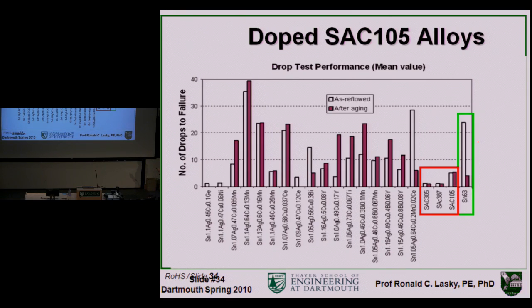So you can see SAC 305 is not too good. SAC 105 is better. But what Dr. Lee found was that if you added just tiny amounts, this is essentially SAC 105 with 0.1% manganese, just tiny amounts of other metals, what are now being called dopants by most of us, can dramatically improve some critical properties. And so this is a whole new field in solder science, which is encouraging, but it's created what a lot of us are dreading, and it's the proliferation of alloys.